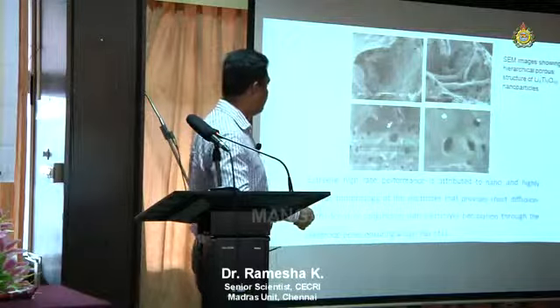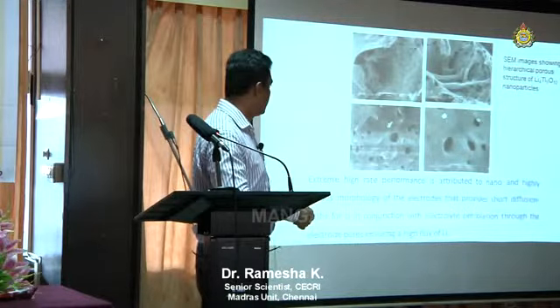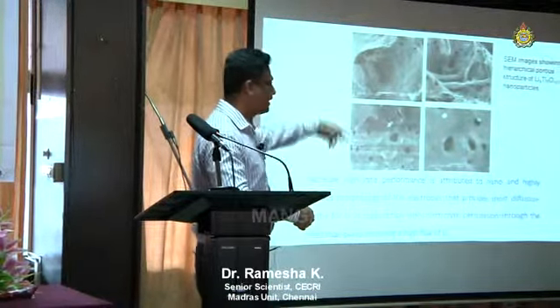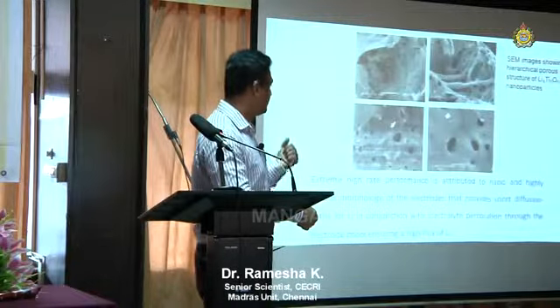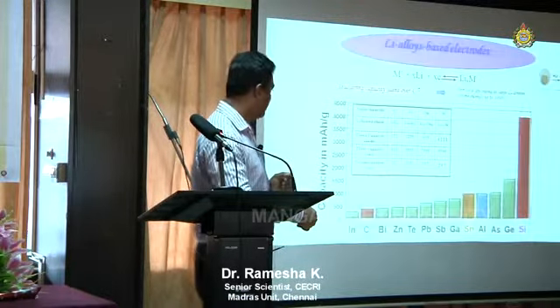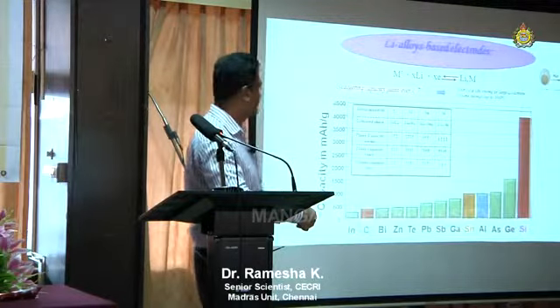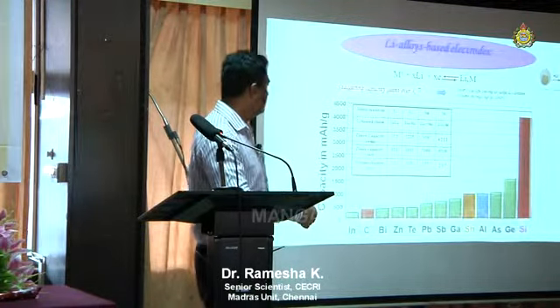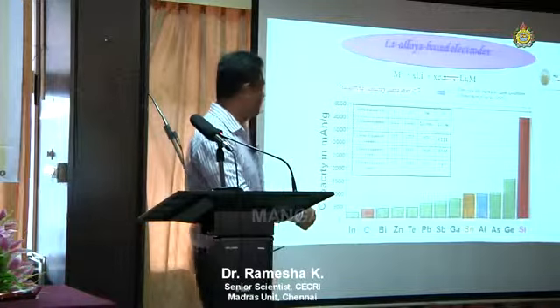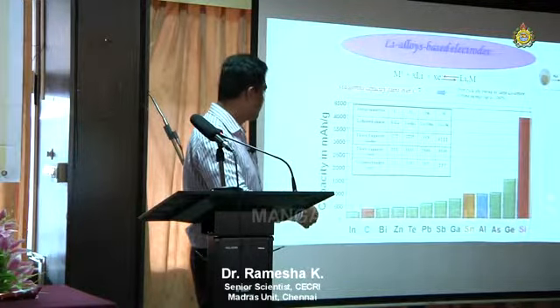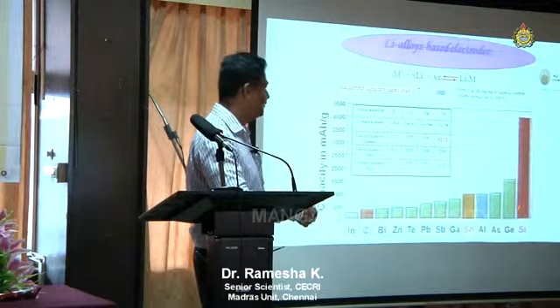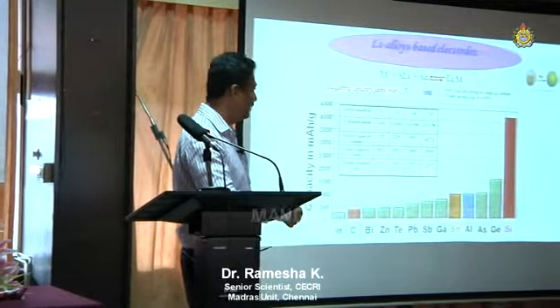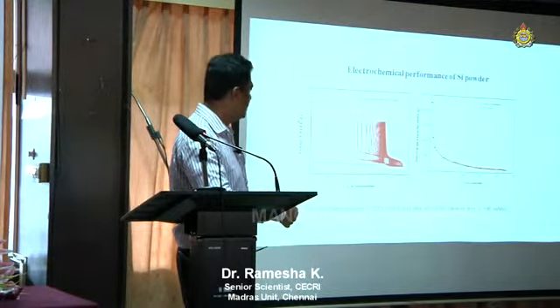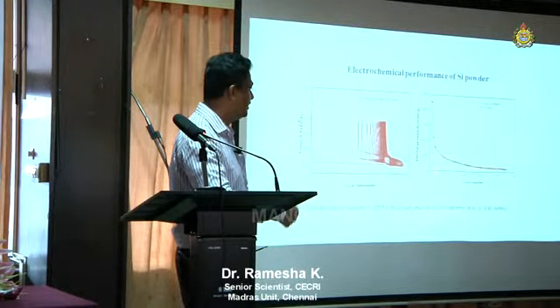You can see that they are fluffy particles and highly porous, so that the electrolyte can pass through, for quick lithium diffusion in this material. A similar issue to what we talked about: those alloying reactions like lithium-tin, though they show very high capacity, actually fail because of the large volume change, 300%. So you go nano. This is silicon, the normal silicon. This is the battery capacity, and within a few cycles the battery is dead. You can see it coming down.